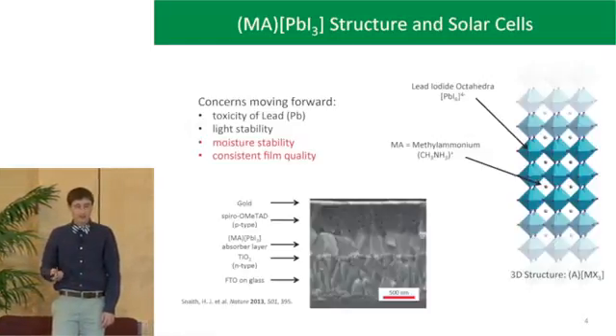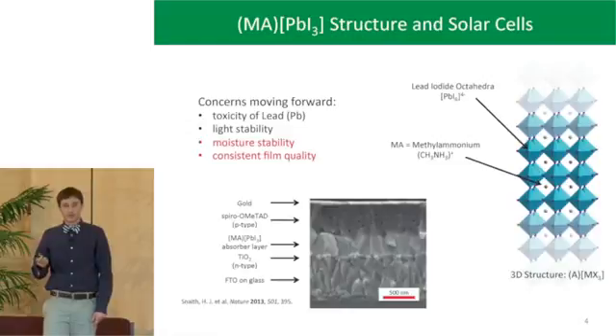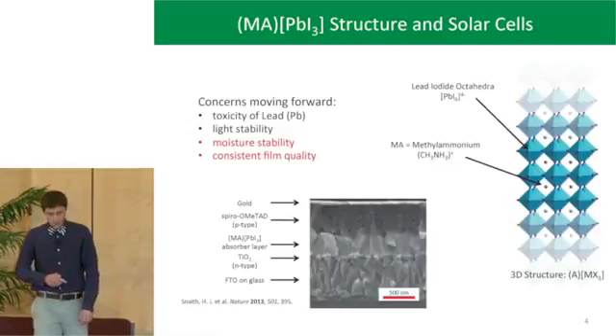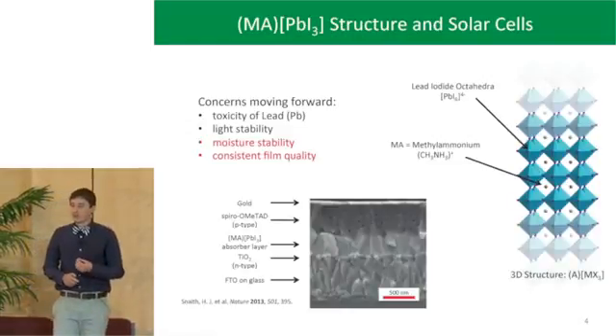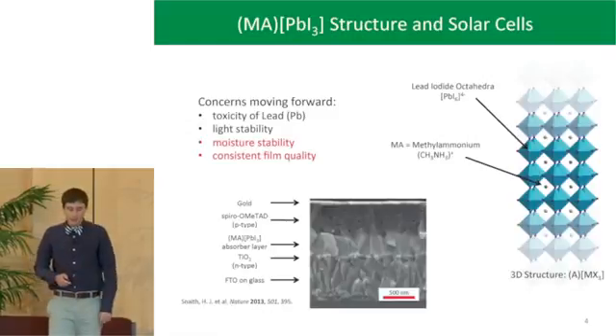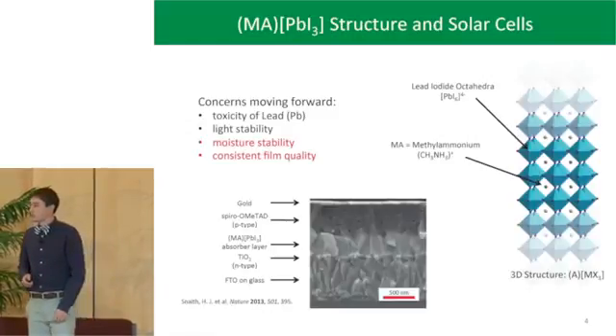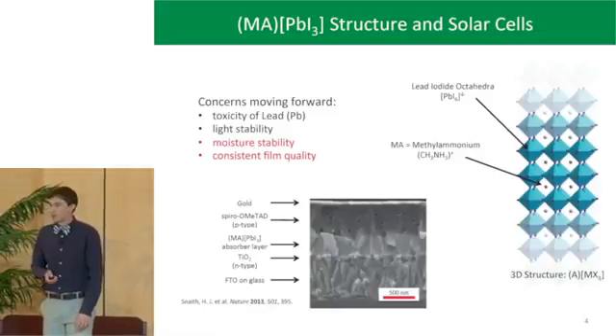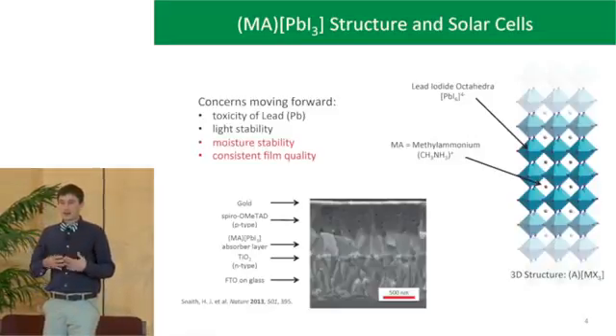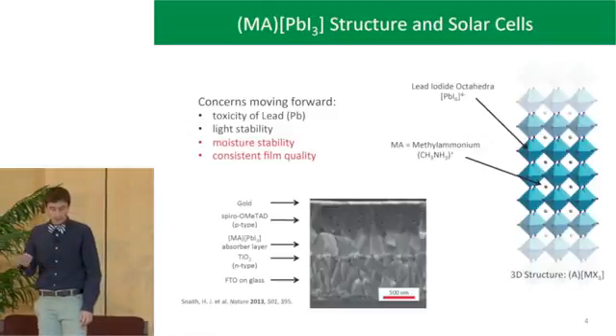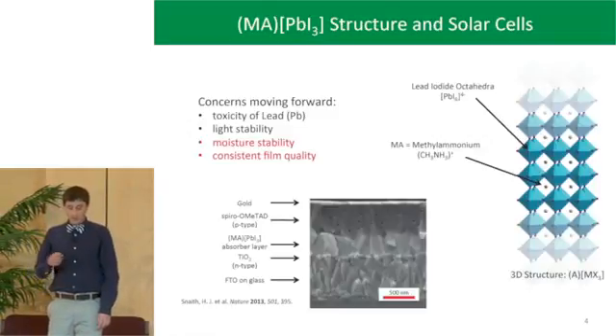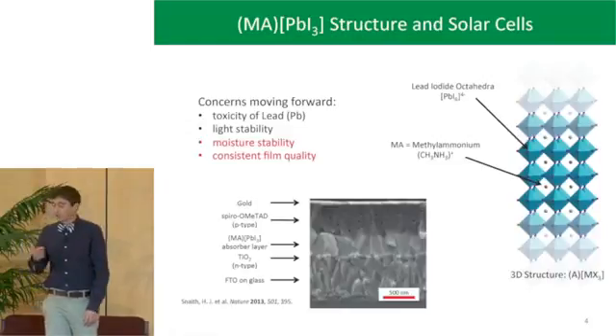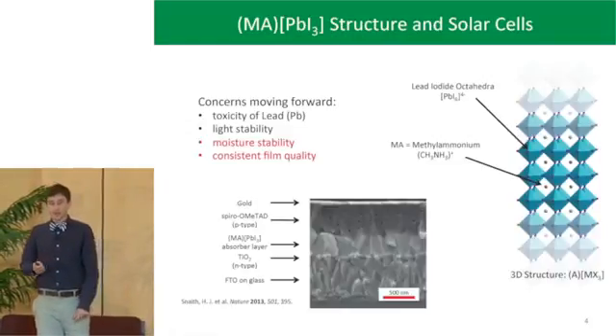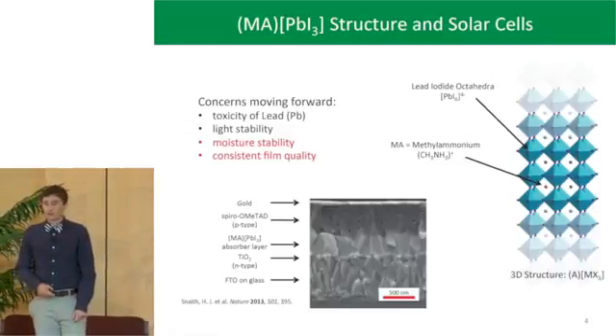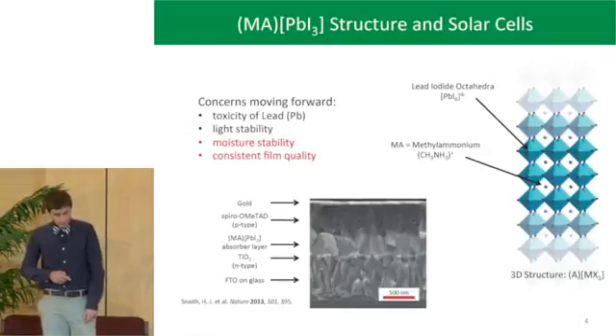One is the toxicity of the lead, especially for a material that is slightly water soluble. And then the stability of the material, both to light and to moisture. So the light issue, Hema talked about earlier, we could see segregation of iodide in the material, potentially decomposition. We don't really know too much about that right now. The moisture stability, though, is really apparent in the laboratory. If you leave a film out, it'll convert fairly quickly.